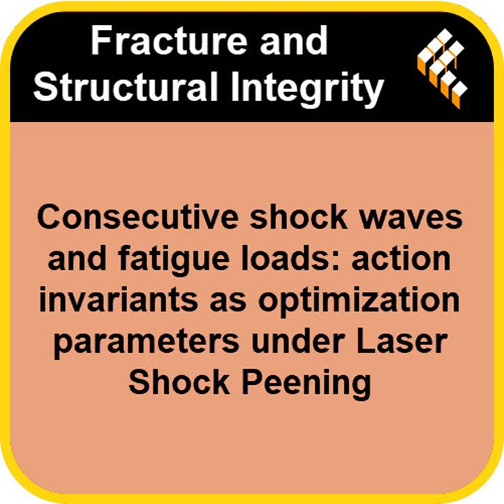Okay. And that energy absorption is tied directly to how defects, like shear bands, form and organize collectively within the material during the shock. So the action invariant is basically measuring the energy that gets stored within those newly created defect structures. In essence, yes. It's a measure of the material state immediately after absorbing that shock energy. It's fundamental to the shock process itself, unlike residual stress, which is more of an after effect. Got it. So for these really high-pressure shock waves, 1 to 10 gigapascals, you need this action invariant to understand what actually happened. You do. It's the appropriate physical quantity for that loading regime.